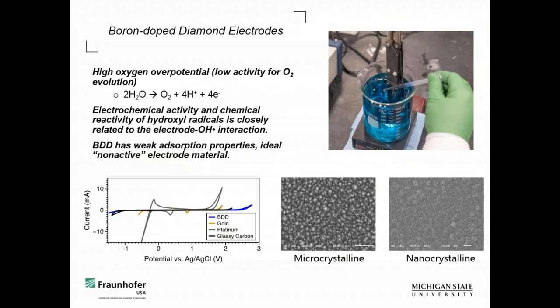But we're using boron doped diamond. So the reason that boron doped diamond is so advantageous is that it has the highest oxygen overpotential of any electrode material that one can use. It's a wide band gap p-type semiconductor, so it's a great anode material.